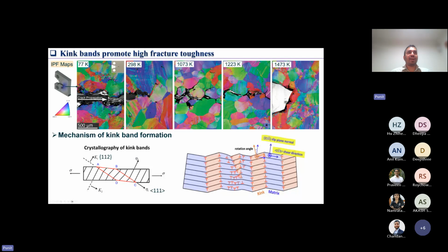So what we see here is that at the crack tip, you have a formation of these kink bands. You have a lot of these kink bands. So what are kink bands? Kink bands form when you apply stresses on this material, by lining up a lot of edge dislocations, which rotates the crystal itself. The rotation of the crystal is such that the crystal is rotating in the direction of maximum critical resolved shear stress. And by doing that, you are maximizing the plasticity inside the material.